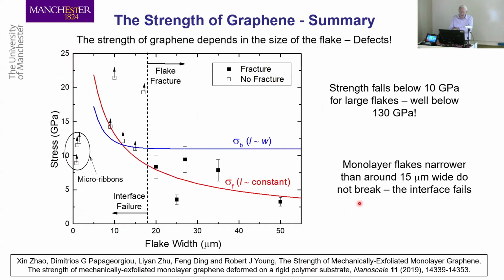against the flake width. The large flakes, we can break them at about 5 to 10 gigapascals. The small flakes, we can't break them because in our setup, the interface fails. The flake just slides. So we have flake fracture for large flakes, and we have intact flakes for small ones. So we find typical strengths below about 10 gigapascals, but very narrow flakes, maybe really quite strong.